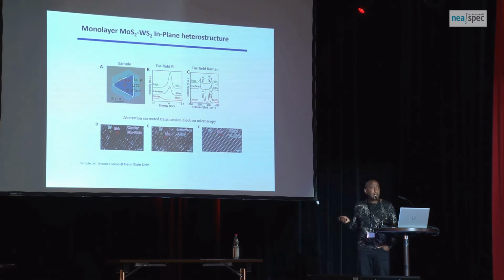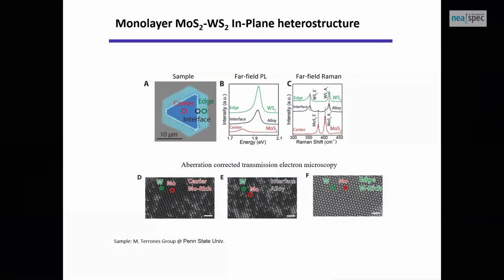of this material, what you find is both the inside and the outside of this material are heavily, the outside is dominantly tungsten disulfide, and the inside is molybdenum rich. Whereas the interface, which is the middle panel here, is quite mixed. So you can see the atoms from both of these materials, tungsten as well as molybdenum. So it's quite an alloyed material. And as I said, this is quite important for what I'm going to tell you.